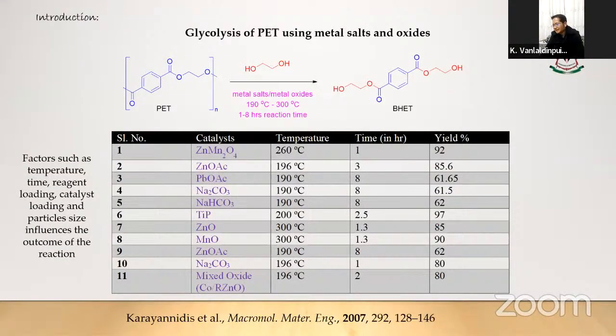So traditionally, glycolysis of PET was carried out using metal salts or metal oxides, and these are some of the examples, some of the catalysts investigated for PET waste recycling. When zinc manganate tetragonal spinel, the first entry, okay, when this catalyst is used at a reaction temperature of 260 degrees Celsius, the reaction was completed within 1 hour, yielding 92% BHET monomer.